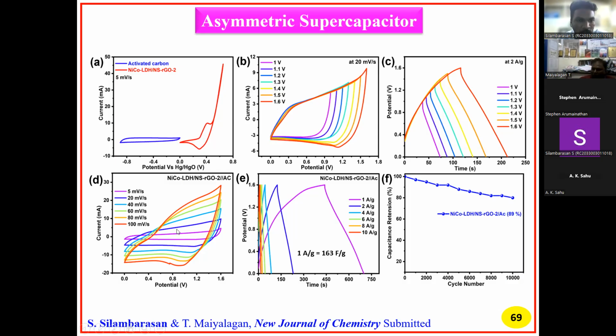Then figure D is the cyclic voltammetry from 5 to 100 millivolt per second at different scan rates. The potential of 0 to 1.6 we measured here. Next, the charge and discharge at a current density of 1 ampere gives around 163 farad per gram. That is the result and the performance. Then the cyclic stability for 10,000 cycles we measured here. The retention percentage is 89%, in the 2 electrode system.